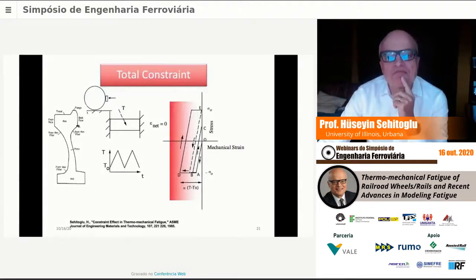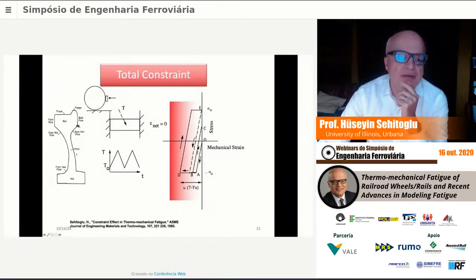Now, I want to discuss the fact that the thermal stresses are generated, at least in the freight wheels, by the application of this brake shoe here at the tread region. So the tread is where the temperatures are highest, this is the rim region, this is the plate, and this is the hub. And you can see here, this is a curved plate, okay? So there's some flexibility here in the wheel to move.